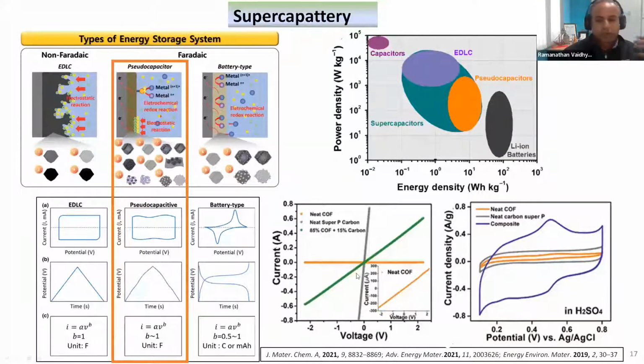Okay, and if you look at a typical COF-based charge storage device, here is an electronic measurement using a 4-probe measurement. What I'm showing you is the neat COF, an actual neat COF, which is a 2D COF. The conductivity is almost negligible. Now, if I want to make this COF useful as a charge storage device, I need to impart conductivity to this. And typically, how do I achieve it? I put conducting carbon in about 15 to 25%, and then immediately you can see the conductivity of the composite goes quite high. And you can see that reflected also in the electrochemical behavior of the composite. The composite electrochemical current is pretty high compared to the neat COF.